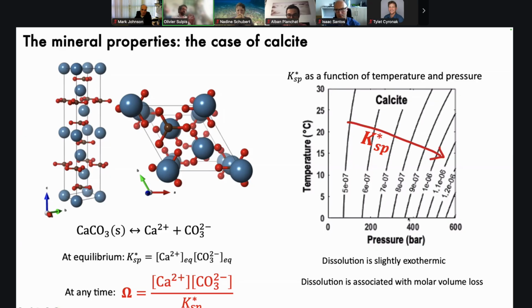The same intuitive process happens with the pressure dependency. The dissolution reaction here frees some room. So basically, it takes more space, more volume, to have crystals sitting in seawater than to have them dissolved, with the dissolved ions hidden in between the water molecules.